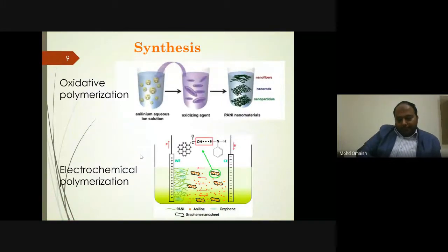And after that, we can see the synthesis of these conducting polymers. Generally, conducting polymers in the lab are synthesized by oxidative polymerization methods. For example, you take some acid solution, you take oxidant, you take monomer, and you can easily polymerize the monomer in the lab. And you can get various morphologies like nanofibers, nanorods, nanoparticles. Another methodology is electrochemical polymerization, where you have a working electrode and a counter electrode, and you get a deposited conductive polymer film.